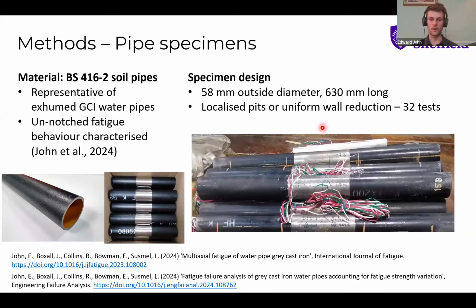So the pipes we tested were all about 2-inch in diameter, so a little bit smaller than pipes we see in the field. This scaling down doesn't really affect anything, because what matters is the stress that the pipes experience. So the stress that these pipes see, if a larger pipe experienced the same stress, then the response would be the same.